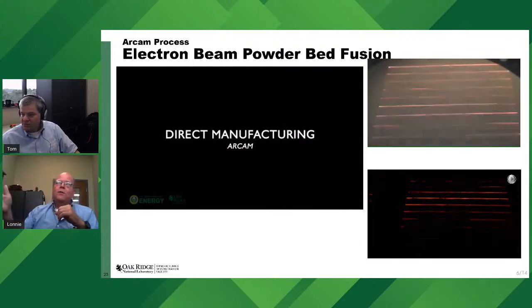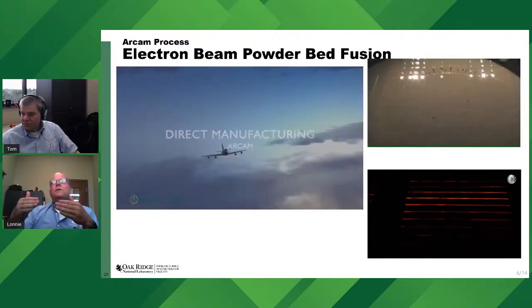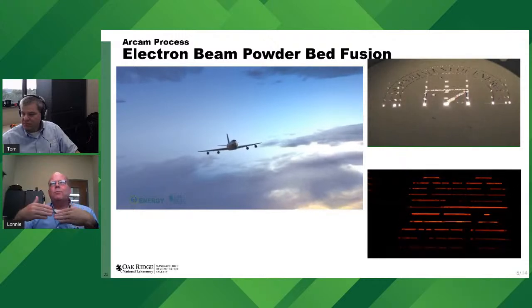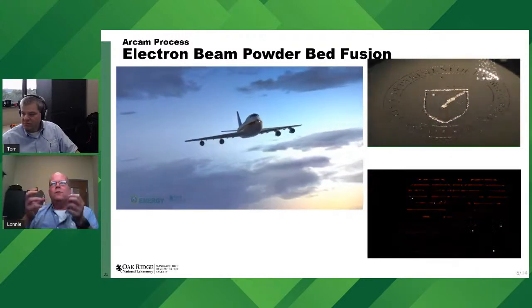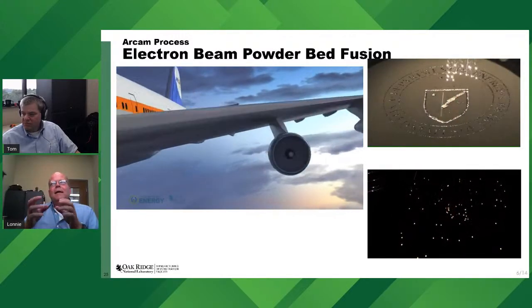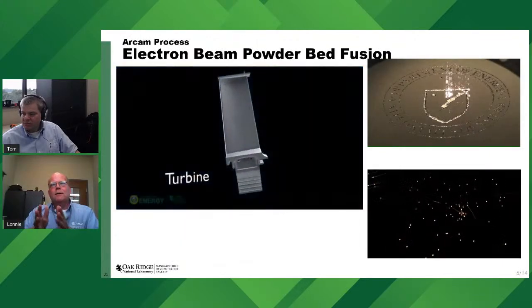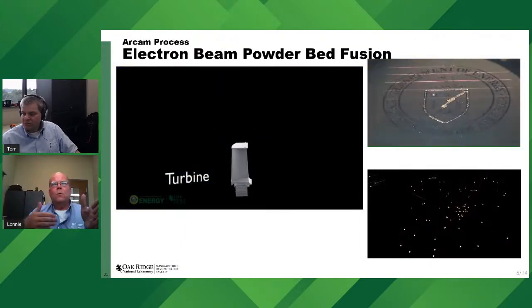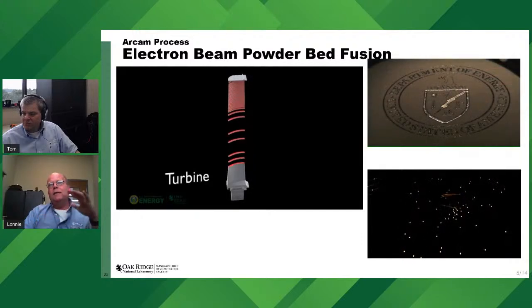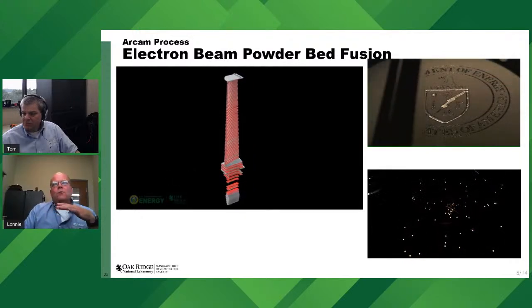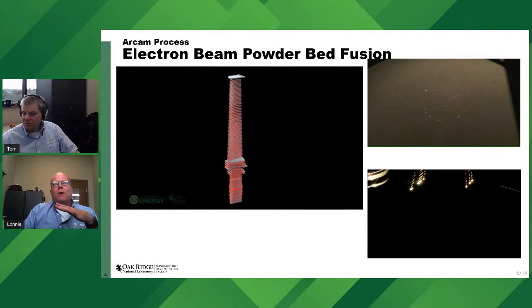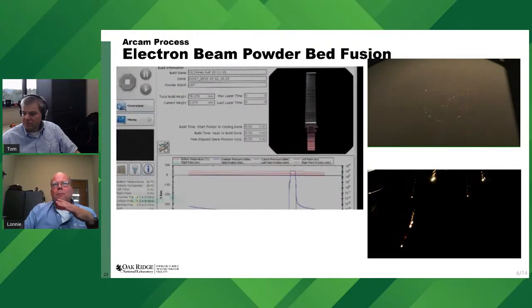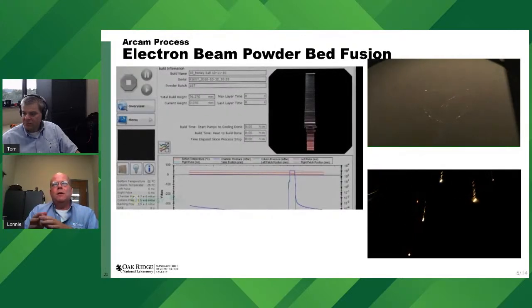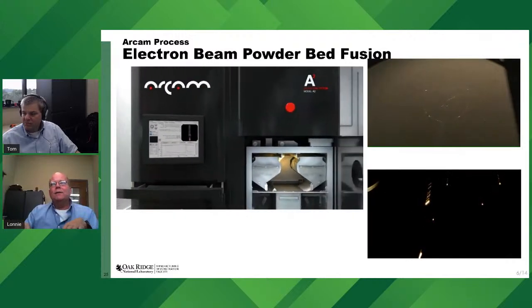So you'll see the raking on the top right. Those lines, it defocuses the E-beam and it's preheating the material, and then you focus it and you weld. The advantage to this process is it's very fast in terms of the welding. A part that may take you a week or 2 weeks to print in a laser powder bed system will take you probably a day to print in the E-beam, because you're able to weld so fast.